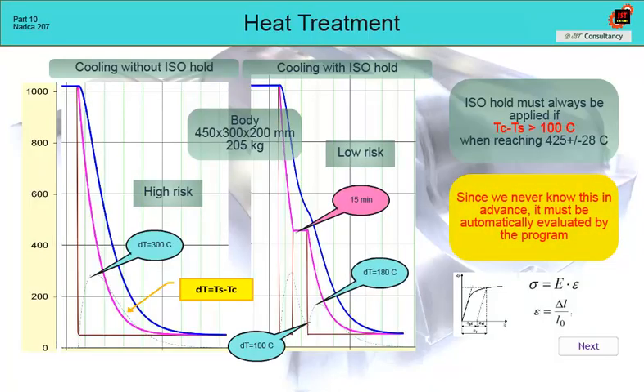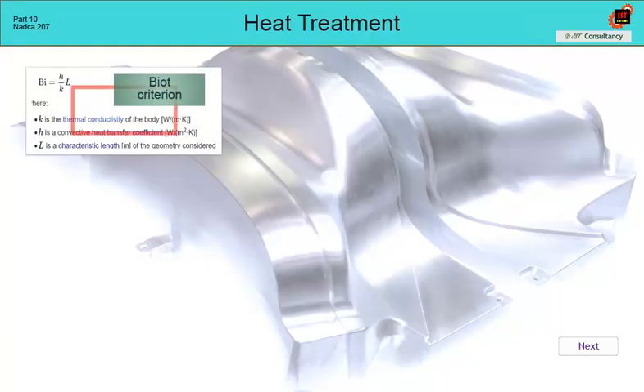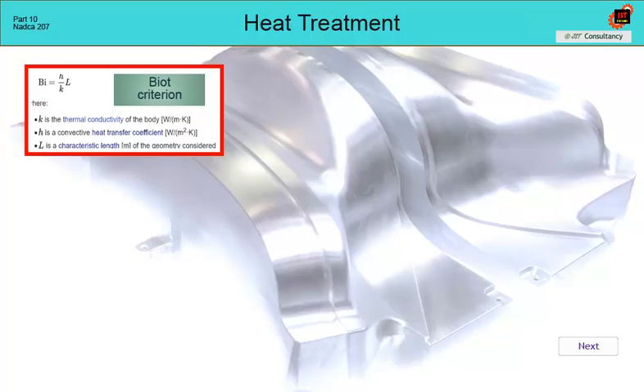To prevent the insert from cracking at this stage, the designer must treat the shapes with the corresponding radii. The question is whether we can predict the necessity of an isothermal hold. There is a so-called Biot number, which is a criterion that tells whether a body is thick or thin from the point of view of heating. For thin bodies, we don't have to take into account the temperature difference. For thick bodies, we have to.